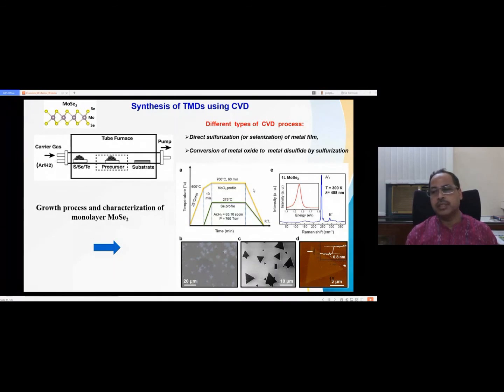So this is the growth parameter of molybdenum diselenide. Here you can see the CVD profile and the growth parameters. This is a typical Raman and PL spectra. This is the characteristic Raman spectrum of molybdenum diselenide. And you can see from the PL spectra, the value is 1.55 eV. This is the monolayer band gap.